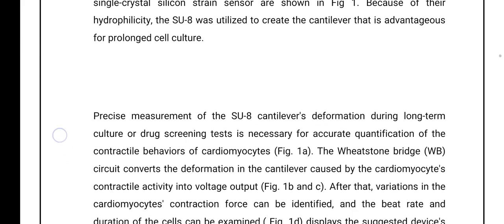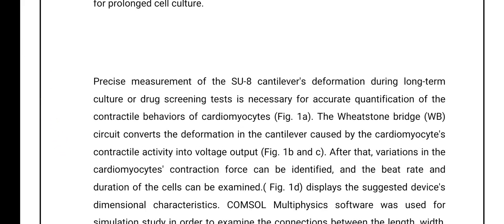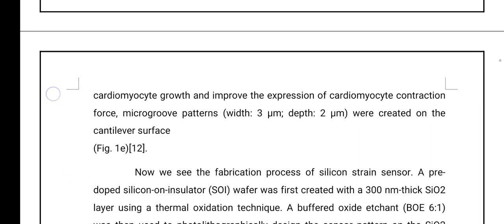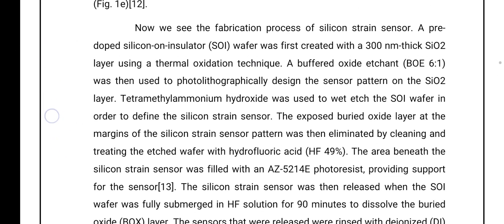Now we will move towards the fabrication process of the silicon strain sensors. First of all, in the first step, a pre-doped silicon on insulator (SOI) wafer was prepared with a 300 nanometer thick silicon dioxide layer using thermal oxidation. In the second step, the SiO2 layer was etched using buffered oxide etchant and photolithography to create the desired sensor pattern. Basically, photolithography is used to get the desired patterns.